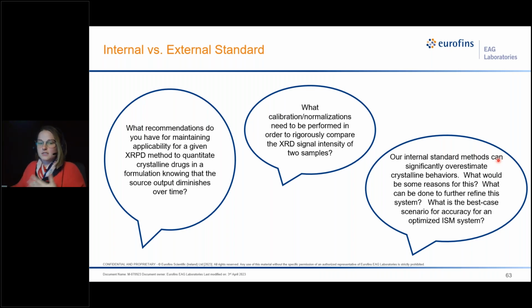So this person is concerned because, let's say, we need to analyze a sample week after week after week. Essentially, your X-ray tube is going to lose intensity over time. The only way to distinguish between your sample deteriorating and losing intensity versus the X-ray tube deteriorating is to use a standard. You can do internal or external, but you use your standard, see the drop in intensity, and subtract that drop from the drop you're seeing in your sample, to make sure the intensity drop isn't happening because of your sample.